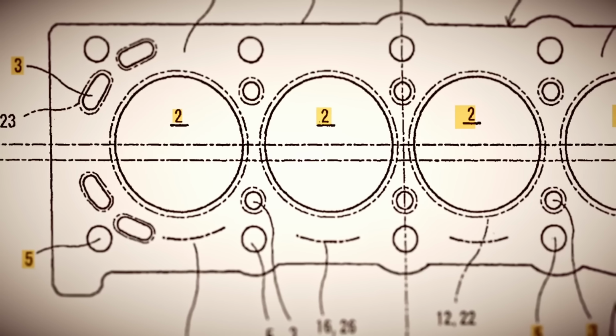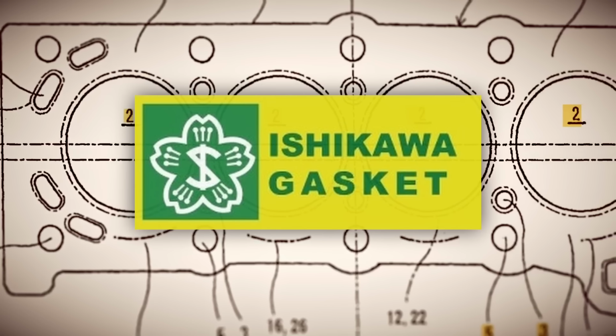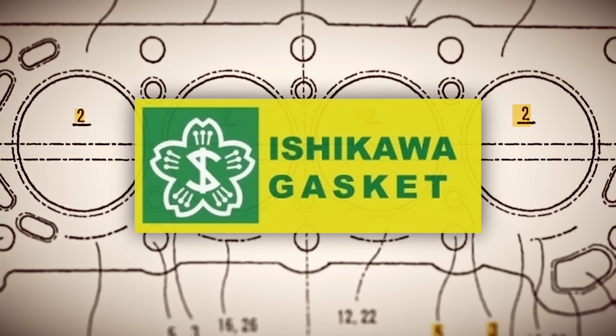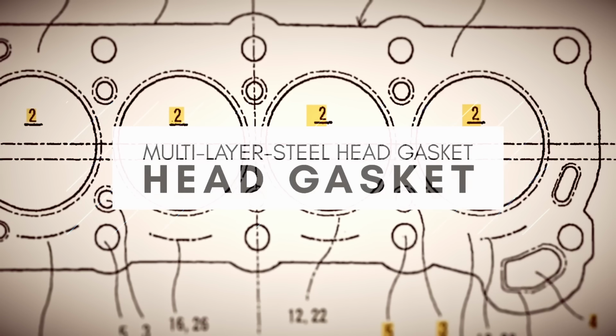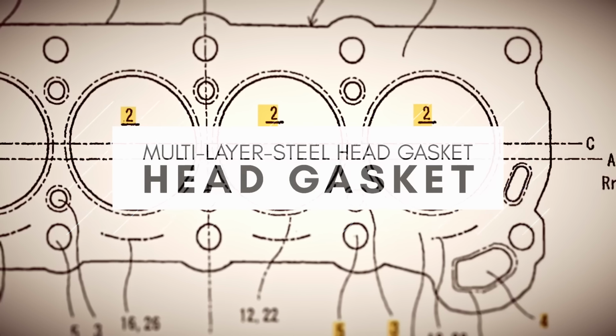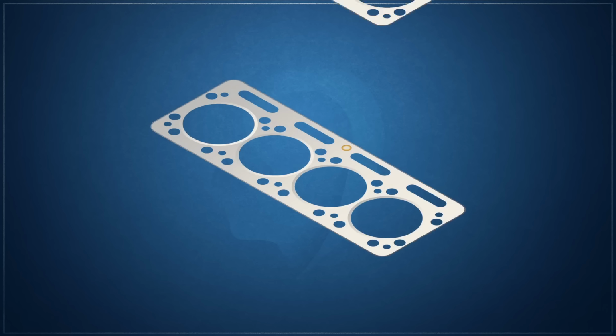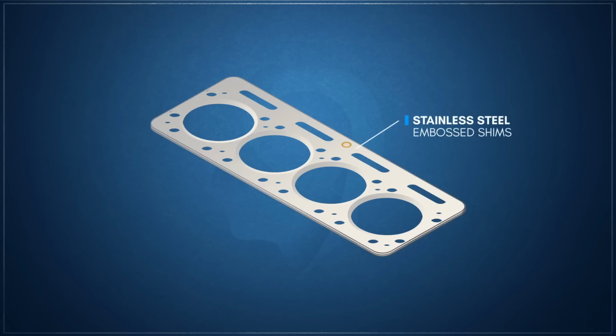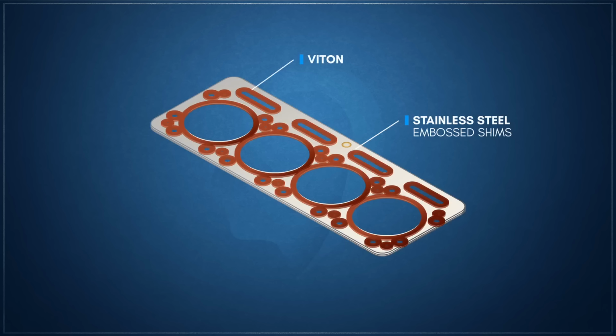In 1970, Japanese gasket maker Ishikawa was issued the first patent for a revolutionary new type of head gasket called the multi-layer steel or MLS head gasket. MLS head gaskets are made from 3 to 7 layers of embossed stainless steel shims that are riveted together, with 3-layer gaskets being the most common configuration. These embossments, when sandwiched together, form a sheet spring that can easily expand and contract in a highly controlled manner. The outer surfaces of the gasket are typically coated with a thin fluorocarbon-based Viton layer in targeted areas to aid in surface sealing, especially for liquids.